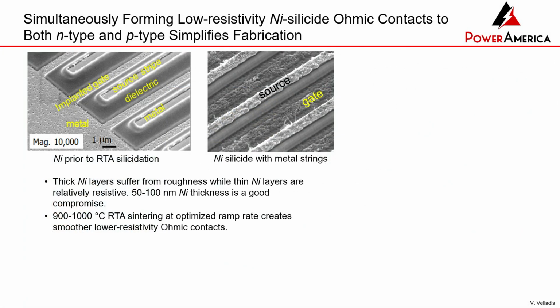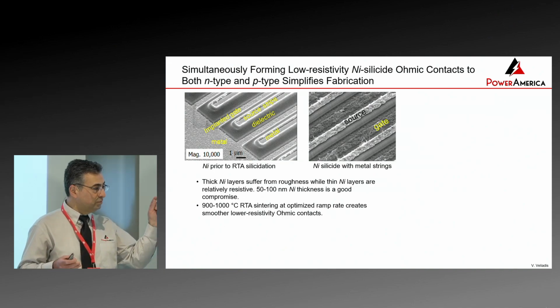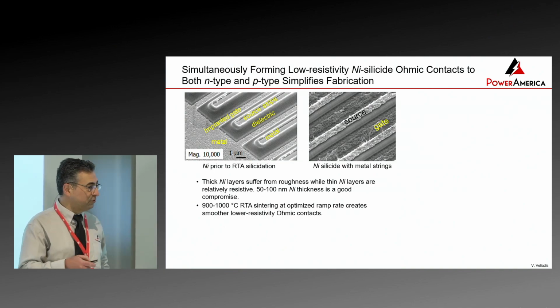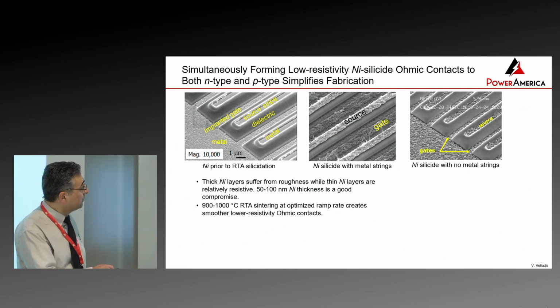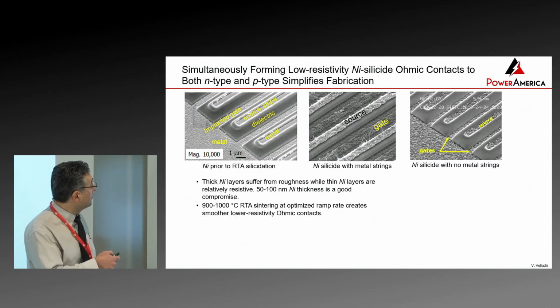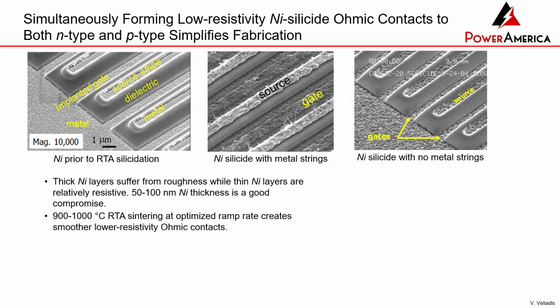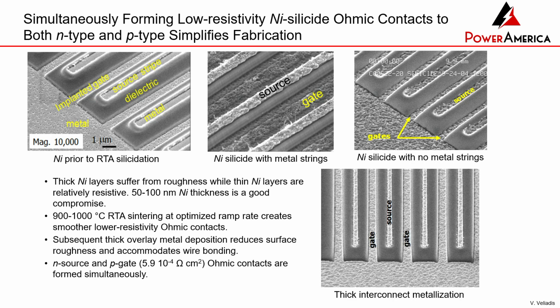And you can see with the silicide, you get these whiskers. So if these whiskers go from gate to source, you got a short. And I saw that, and it got shorted, and I put it in the oven, brought it to high temperature just to kind of melt those connections away, and the device worked. But this is basically going from here with this glass separation. You get a nice silicide, low ohmic contacts, and you put a thick metal, and you're done with that.